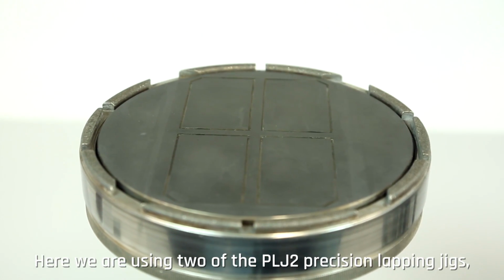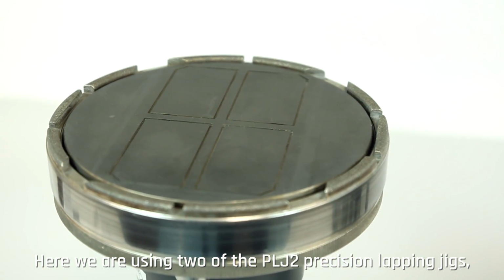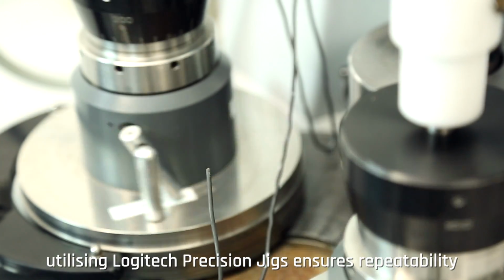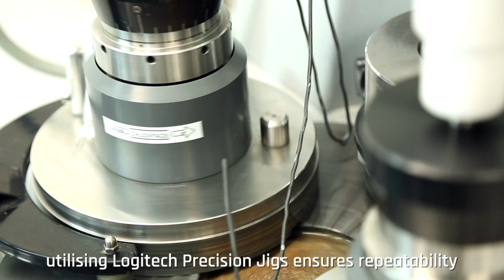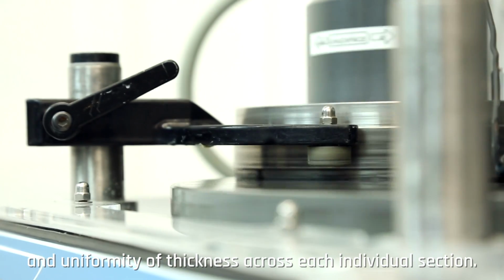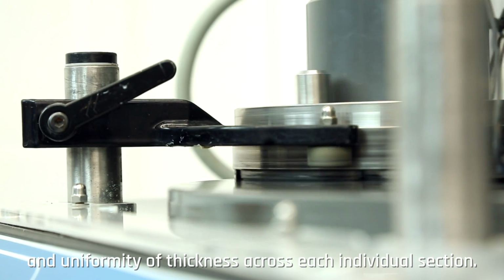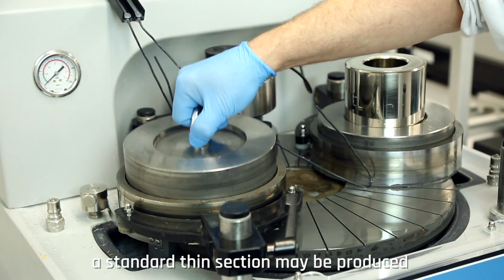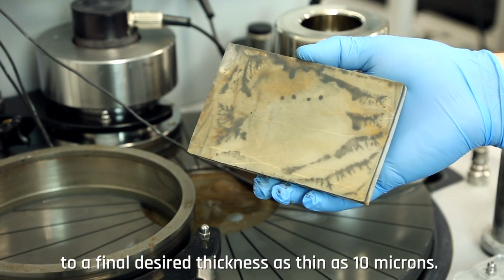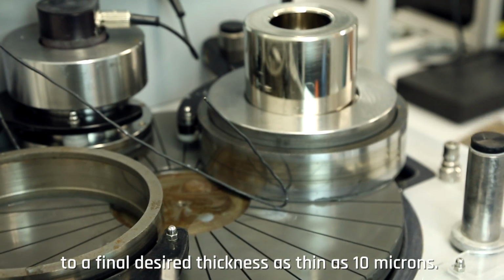Here, we are using 2 PLJ2 precision lapping jigs. Utilising Logitech precision jigs ensures repeatability and uniformity of thickness across each individual section. Through this method, a standard thin section may be produced to a final desired thickness as thin as 10 microns.